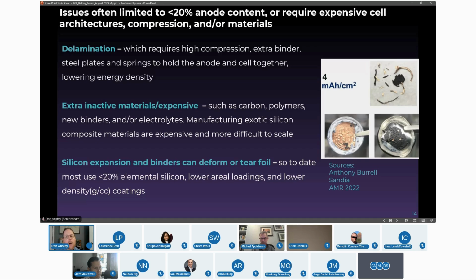And Ben, thank you for the comment. Yes, Silion was acquired by Tesla, and that was a metallurgic grade silicon, and Tesla was not able to hit cycle life. I'm not saying that means no metallurgic silicon company will ever hit cycle life, but they were unable to hit cycle life, and now they are looking at other silicon materials that can hit acceptable cycle life. Another company working on metallurgic is Coreshell, and they've hit about 300 cycles against LFP. But if you need to get the energy up and you're only going to be sub 500 cycles, you've got to switch from LFP probably to high nickel.